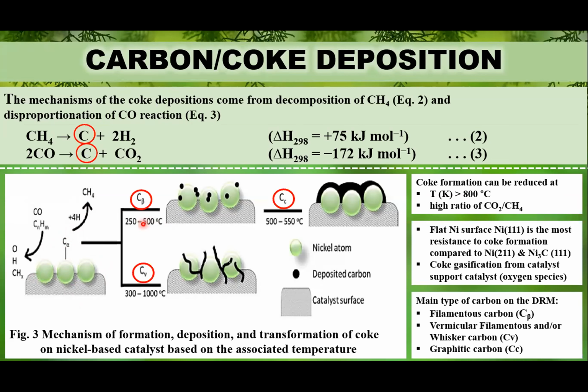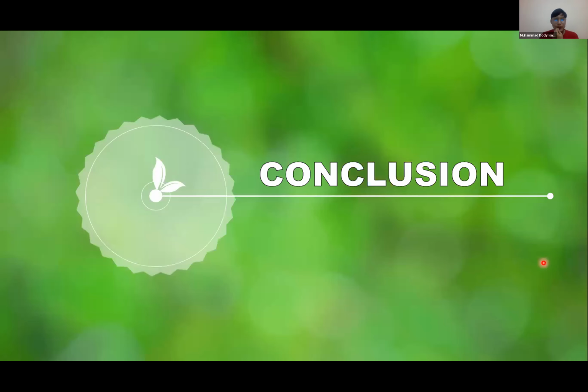and then at higher temperature, like 250 to 500, it can become filamentous carbon, and it can further polymerize into graphitic carbon. And also whisker carbon, which forms from 300 to 1000, which can also promote the activation process. And the most resistant is nickel with a flat surface, nickel 111, which is the most resistant compared to nickel step, nickel 211, and nickel carbide.